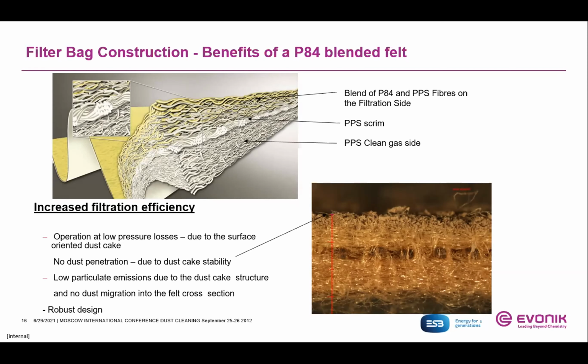We see that there is a certain dust layer on this fabric, and the dust layer is near the surface. So it's not a straight line. Of course, it has some penetration into the construction, but it should be near the surface. And the reason why this is so important is the following.